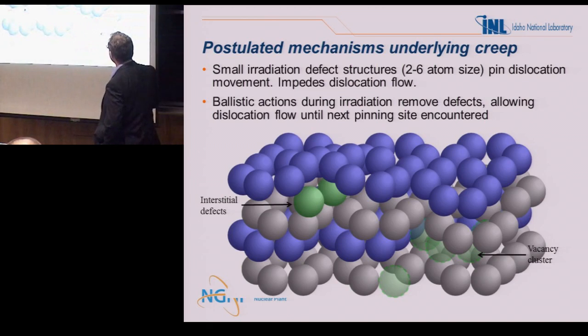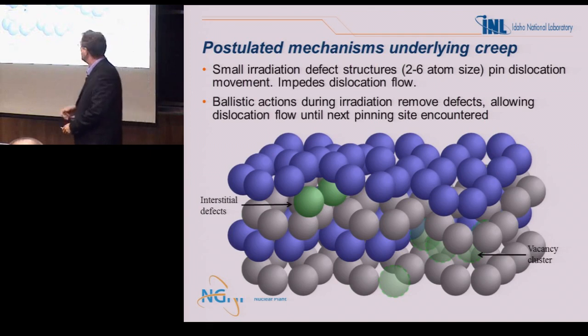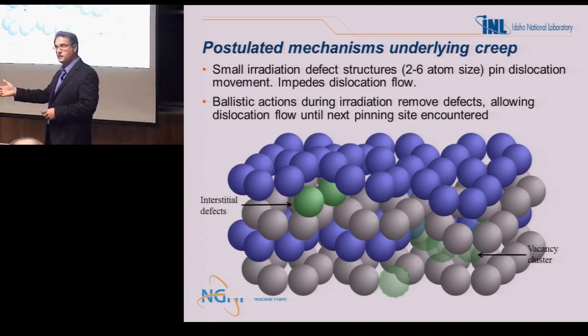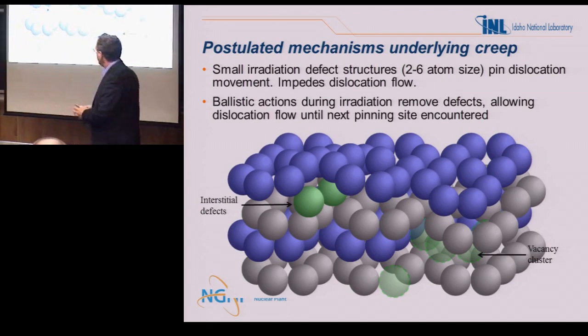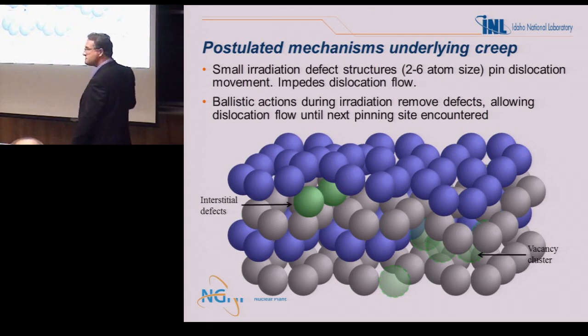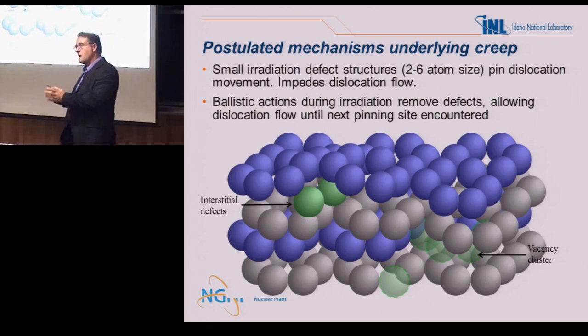Okay. Postulated mechanisms for understanding creep. So these small irradiation defects, remember these interstitial atoms in between and specifically the vacancy clusters, well, what they do is they interrupt the dislocation flow, all right? Under irradiation, it blows these things out and rearranges the atoms and allows the dislocation to flow. It's called a pinning, unpinning mechanism.